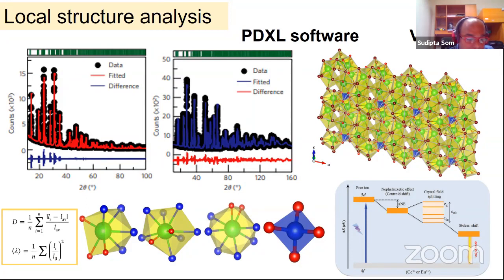What was our primary aim? From this we can get how many sites are available for the rare earth to be substituted. For example, we have 3 strontium sites available here for Eu or Ce3+ to be substituted. And we know that the nephelauxetic effect and crystal field splitting are the deciding factors for the emission color. As we have 3 different kinds of sites available, our emission color also will be different. For example, we can get 3 kinds of wavelengths from similar phosphors. Those are expected to be obtained.